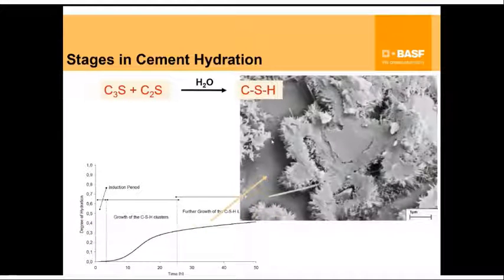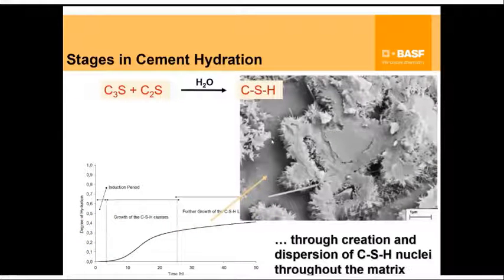Next. And here's a picture, an SEM image of a cement grain in the middle, and you can see the CSH being deposited all around it. And so basically, this is how cement hydration proceeds in order to get to CSH particles, which then give strength properties as well as other properties to concrete. Next.